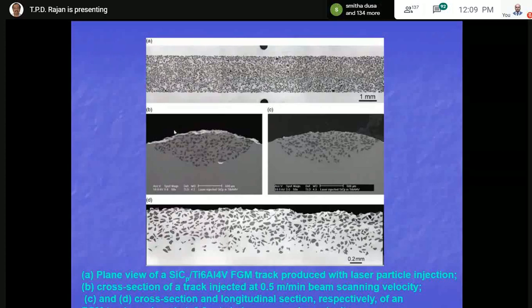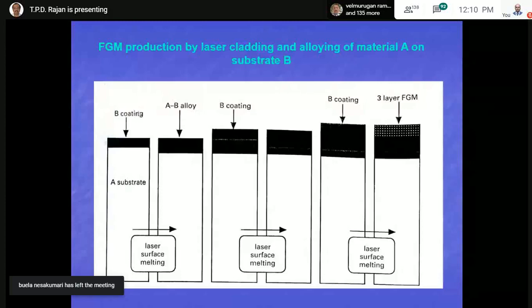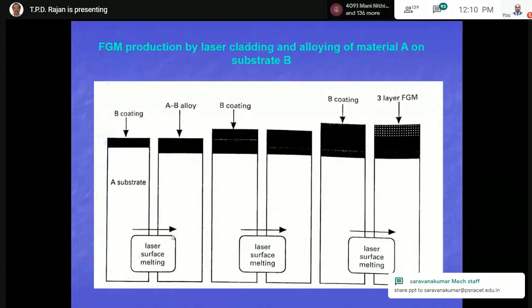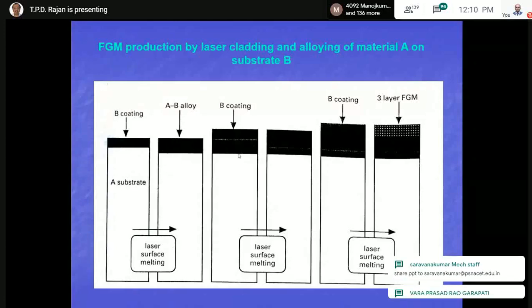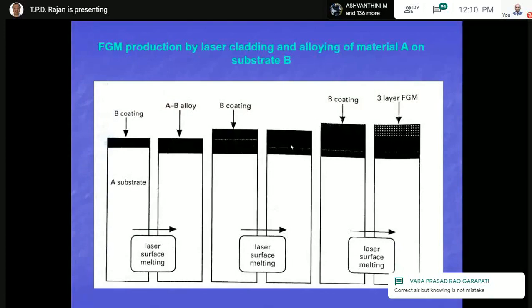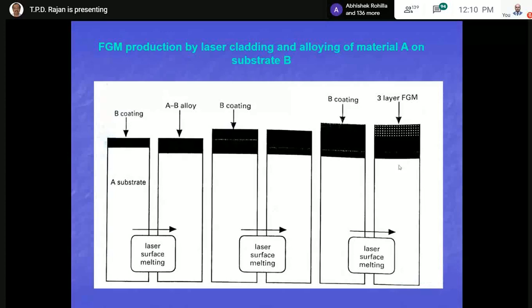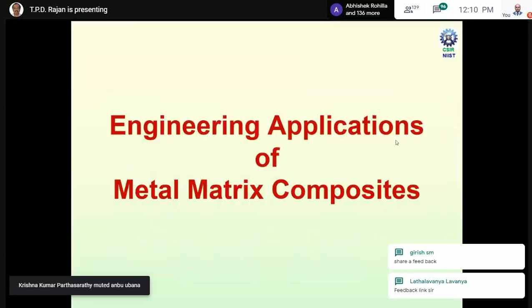This is a top surface, and this is a cut cross section. We can see this is a graded formation of silicon carbide particles in a titanium 6 aluminum 4 vanadium composite system. Similarly, laser cladding also can be used. That means you coat the substrate A with B, then you pass the laser, and this gets melted and mixed. Similarly, B can be again melted. So a layer richer in B will increase, and finally you will end up with a layer complete with B. So this is also possible.